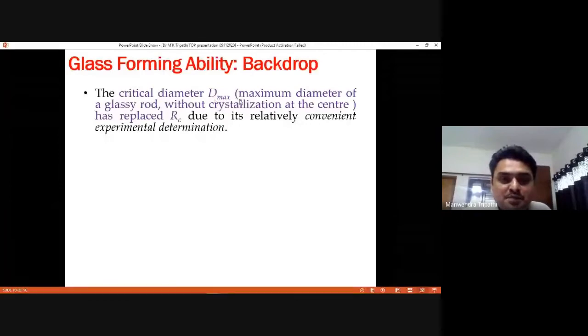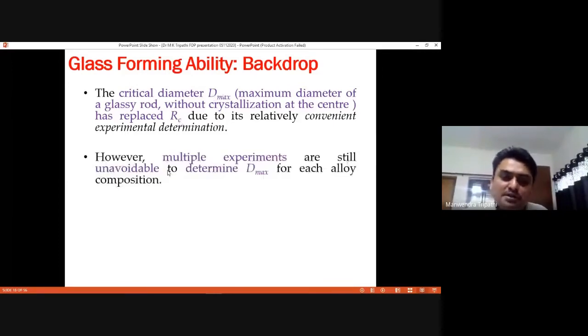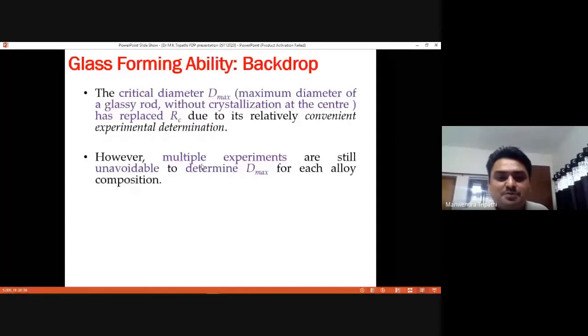So what is critical diameter? Dmax. Sometimes we write it as Dc or Dmax. That is the maximum diameter of a glassy rod without crystallization at the center. And now Dmax has replaced Rc due to relatively convenient experimental determination. It is easy to capture Dmax rather than Rc. But then there are other difficulties. Multiple experiments are still unavoidable to determine Dmax. You have to make multiple experiments to determine where you are getting Dmax.